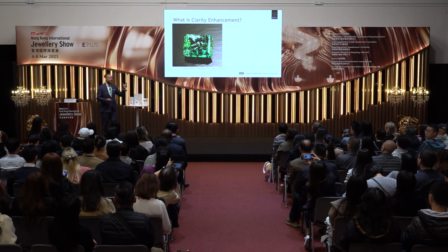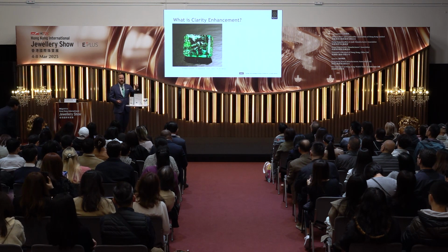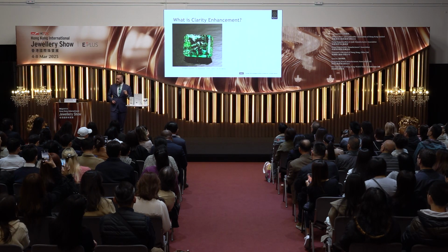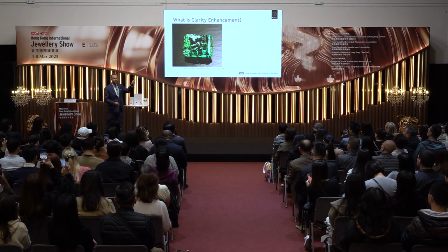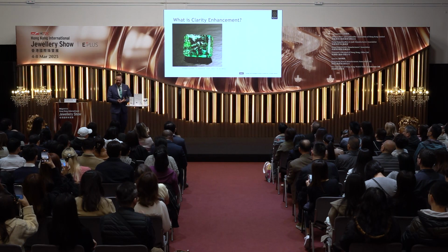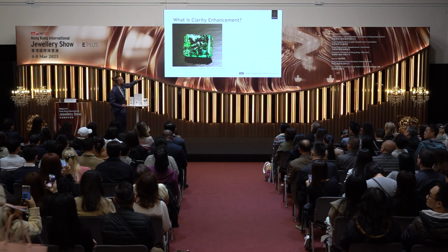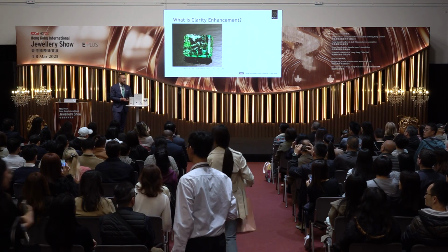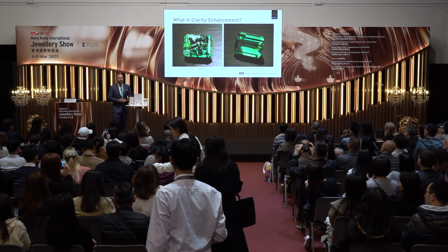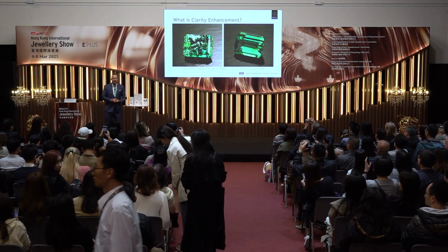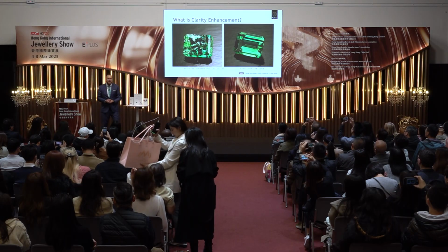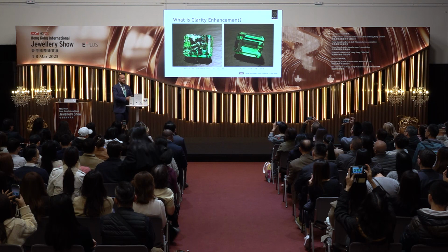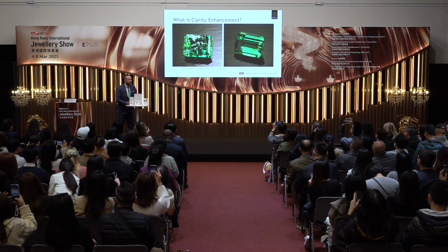And I can show you what the impact of that could be, and I think why you also realize that it's important to tell your client about this. Because this is an emerald that has no filler in it. It has not been clarity enhanced. So we can see all the fractures there, and we can see all these reflections of the fractures, those big broad flashes. This is that same emerald after we clarity enhanced it. So this is the same stone. That is why disclosure is very important. But that is also the impact that clarity enhancement could have.